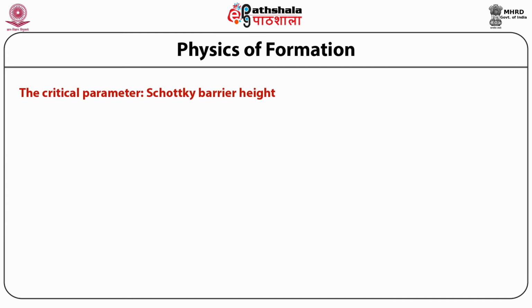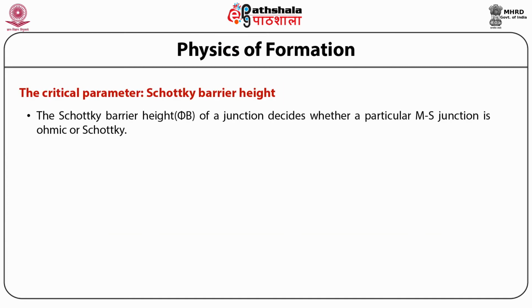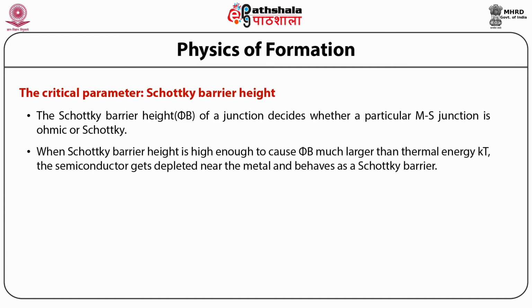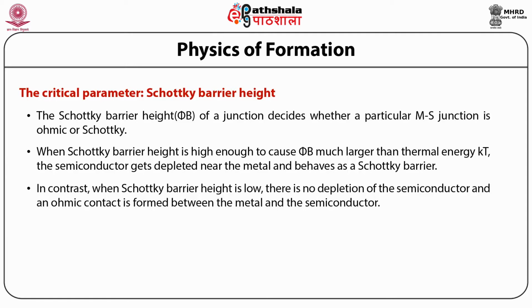The critical parameter, Schottky barrier height. The Schottky barrier height, denoted as phi b, of a junction decides whether a particular MS junction is ohmic or Schottky. When the Schottky barrier height is high enough to cause phi b to be much larger than the thermal energy kT, the semiconductor gets depleted near the metal and behaves as a Schottky barrier. In contrast, when the Schottky barrier height is low, there is no depletion of the semiconductor and an ohmic contact is formed between the metal and the semiconductor.